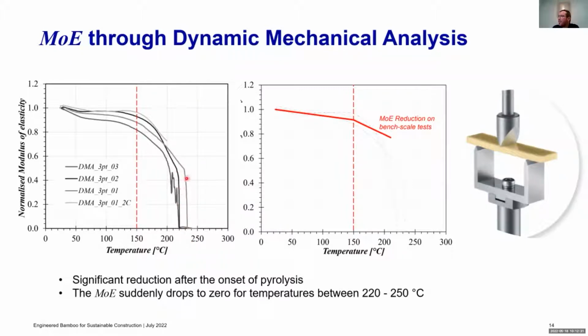And then what you can see here is that I compared the results of the bench scale tests, because I measured the modulus of elasticity in both the compressive and the tensile strength tests, against the DMA results. And you can see a really good fit between the bench scale tests and the DMA results.